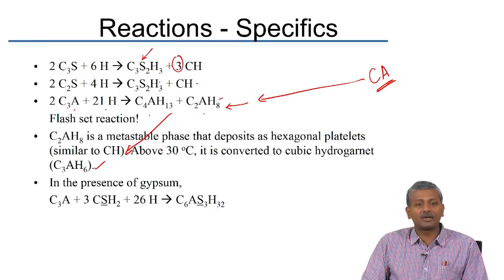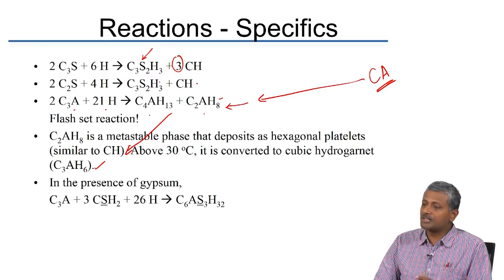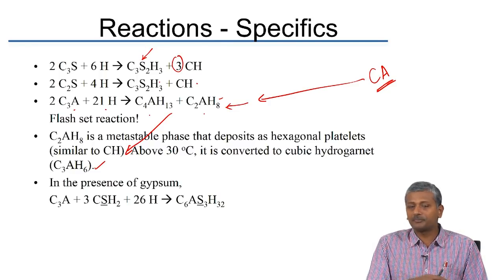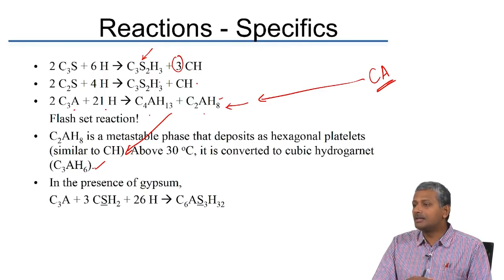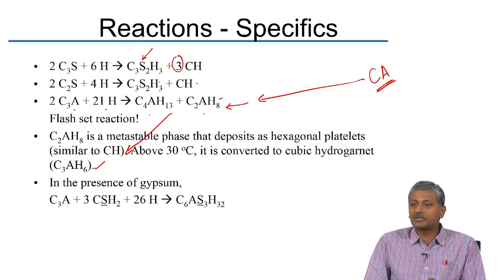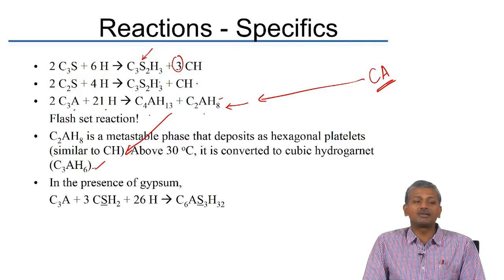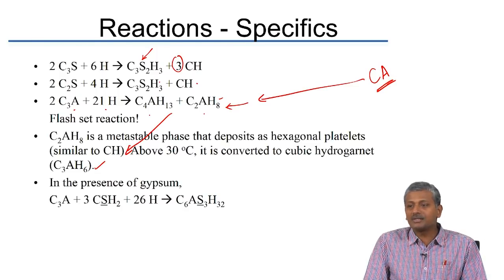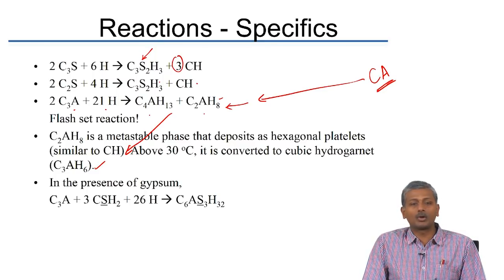Because of structural collapses, calcium aluminate cement fell out of favour for general construction. Today it is used only for specific high-temperature applications — for example, lining cement kilns at temperatures around 1000°C, where the phases formed have excellent heat-resistant properties. For general construction it is not suitable because at moderate temperatures of 25–30°C the hydrated structure changes, causing strength and durability reduction. Below about 15°C this conversion would not occur.